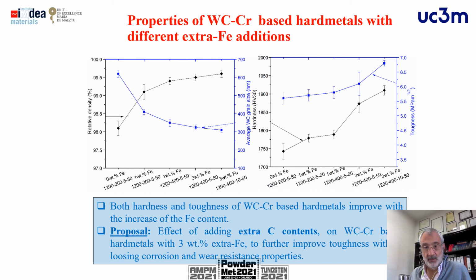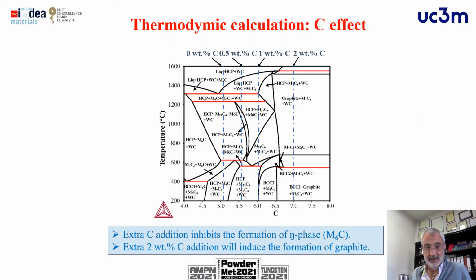So here you can see also the toughness that we can reach with this 3% of iron, and you see that we have increased a little bit the toughness that we got with the liquid phase sintering, that was lower than this value near to 6. So also the hardness can reach some high levels, and from these values of 3% of iron, we add different contents of carbon.